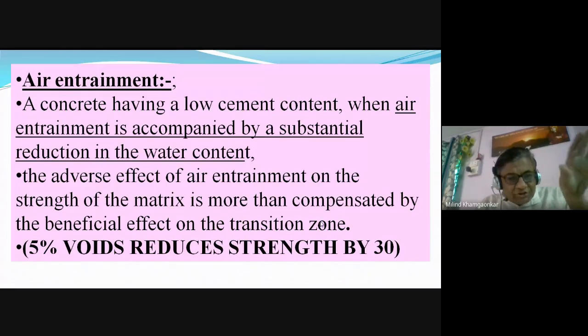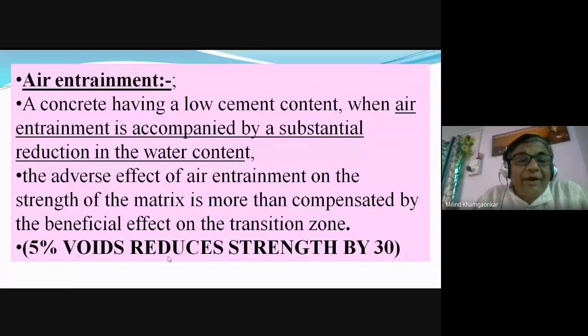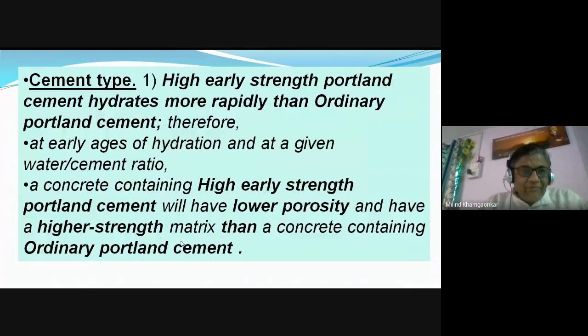At this juncture, just we will keep in mind that concrete matrix or the combination of all these ingredients have one zone which is near the aggregate called as the transition zone. So again, improper, inadequate compaction or more entrainment, 5% voids reduces the strength by 15 to 30 kilogram per centimeter square strength. So the voids are very important.